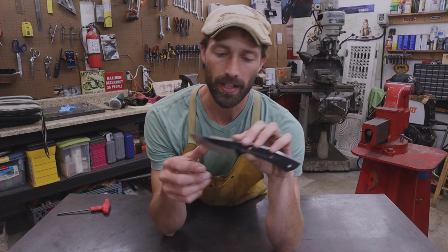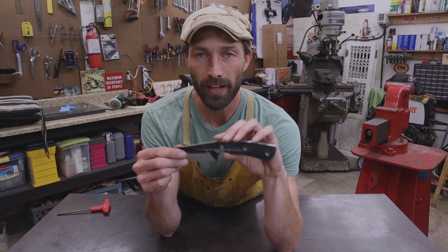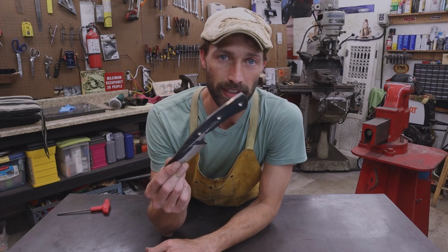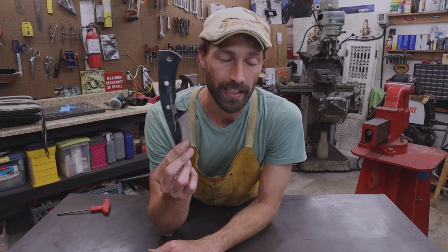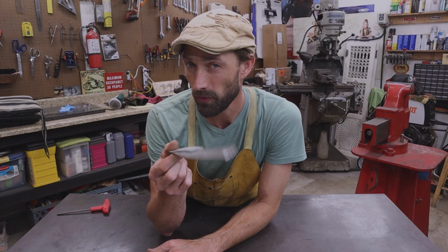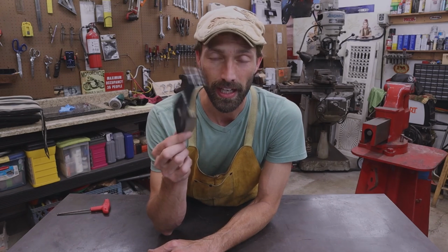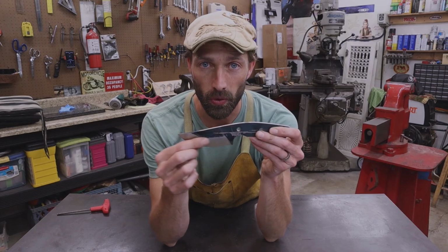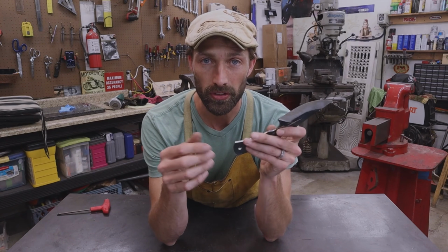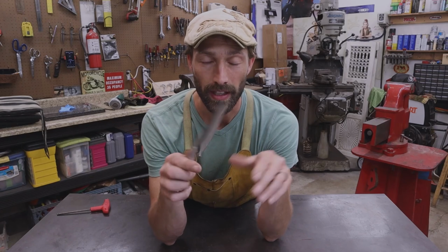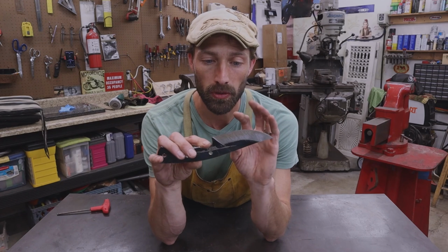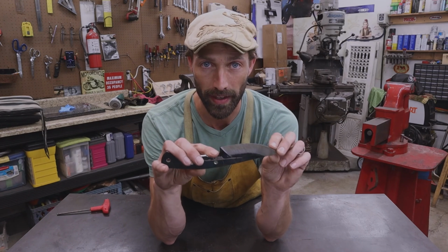Now on the heat treating process, for a new knife maker, let's make this super easy. All you're gonna need is a torch or a forge. I'm gonna use my forge, but you could very easily heat this with a torch in the exact same fashion. And then you're gonna heat it till it's non-magnetic. So all you need is a magnet and a torch. And you're gonna slowly heat the edge with your torch until when you hold it to the magnet, it doesn't stick anymore. And that's gonna tell you that the metal is moved into solution and it's ready to be quenched.